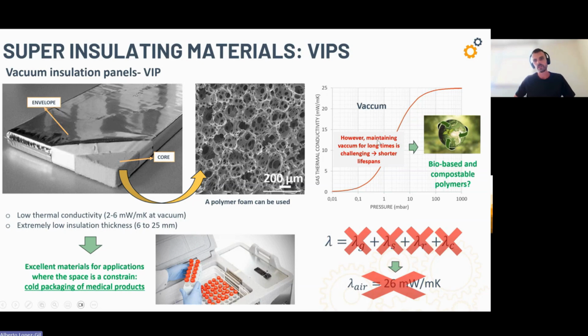One issue of vacuum insulation panel is that maintaining vacuum for long times is not easy. It's because this aluminum layer in many cases is broken during the use of the product, and then we have air again inside the foam. So the lifespan of this product, as opposed to other thermal insulation materials, for instance in the building sector, is shorter. So this is again a new opportunity for bio-based and maybe in this case compostable polymers. And another issue with vacuum insulation panels is that very high vacuum pressures are needed to remove the air inside, as you can see here.